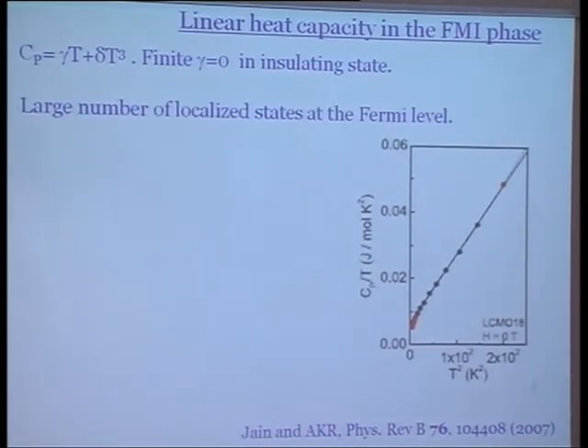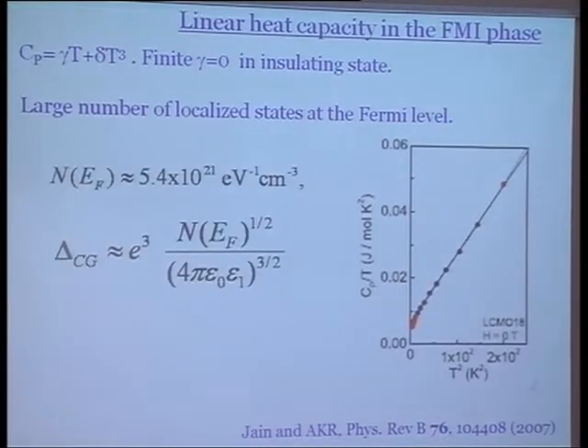Now, this means that I have a lot of localized states at the Fermi level. If I calculate from this the density of states at the Fermi level, which this gamma gives me, I can use a simple free electron approximation. I can find out the value of the Coulomb gap from this simple relation. And when we do that, I get a very interesting number, in the ballpark of about 100 meV.